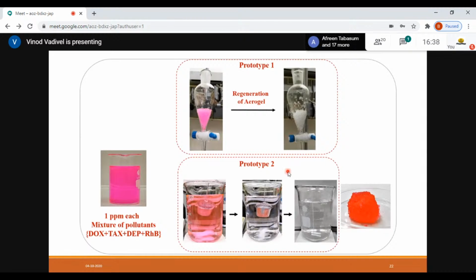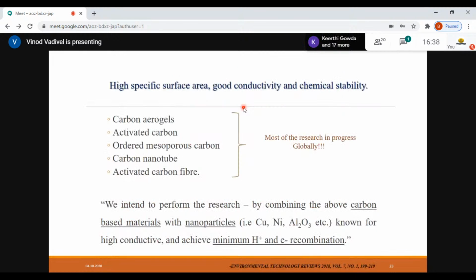So the prototype was very clear for commercial purposes and also for real-time applications, because aerogels cannot be used in a one-time system. You need to demonstrate the efficiency of this particular aerogel multiple times, at least 5 to 6 times, to compensate for the cost of synthesis of this particular material. So we found almost 5 times regeneration is happening, and for some chemotherapeutic drugs it was almost 10 to 20 times, and the results are yet to be published.